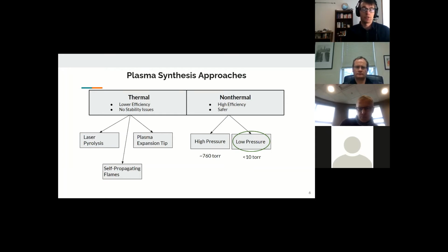While not all DC plasmas are thermal, the plasma in the expansion synthesis process is thermal because of the morphological requirements of the reactor. Finally, the technique used in this thesis is the non-thermal plasma process. This has been performed before by several research groups to achieve hollow crystalline silicon carbide nanocrystals in low pressure plasmas, amorphous silicon carbide nanoparticles in low pressure plasmas, and both amorphous and crystalline silicon carbide nanoparticles in atmospheric pressure non-thermal plasmas. But silicon carbide nanocrystals have never been made directly in a low pressure non-thermal plasma, which is the motivation for this thesis.